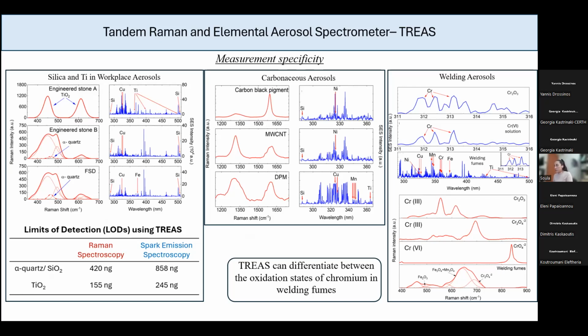It has different recommended and permissible exposure limits, and it's of high significance to be able to detect specifically chromium-6. When we use spark-emission spectroscopy that sees only the elements, we cannot differentiate. We can see the chromium in all cases, but we cannot identify the oxidation state. But when we do Raman analysis, for example, in the top 3